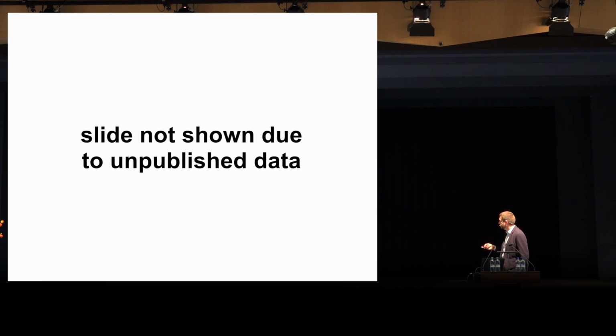So within the PhD thesis of Marie-Claude, we looked at how ionic transport is related to microstructure. You can see here, as a function of sintering conditions at a lower temperature, we get relatively porous structures where the sodium ions have to follow a tortuous path to reach the other side, so the conductivity is relatively low.